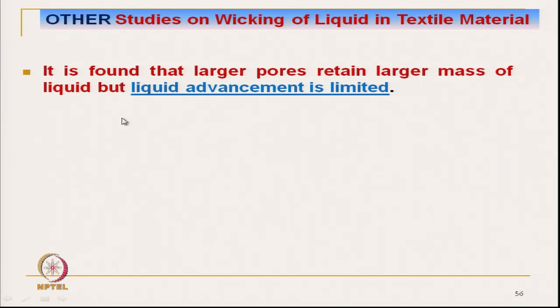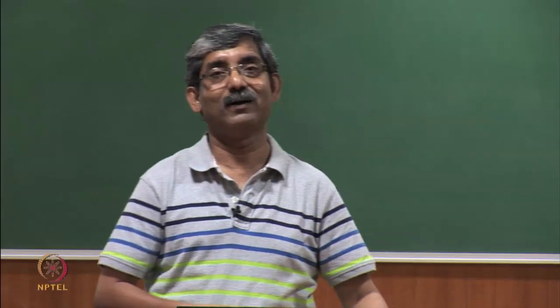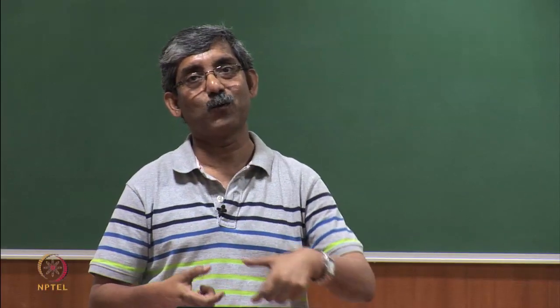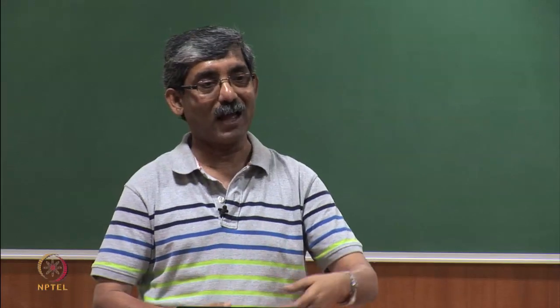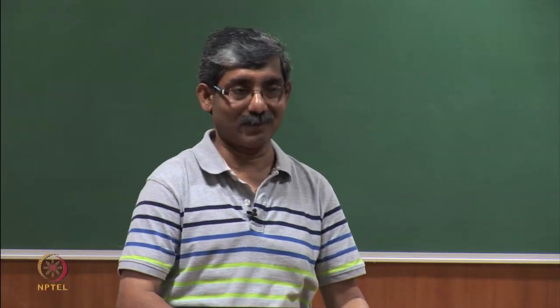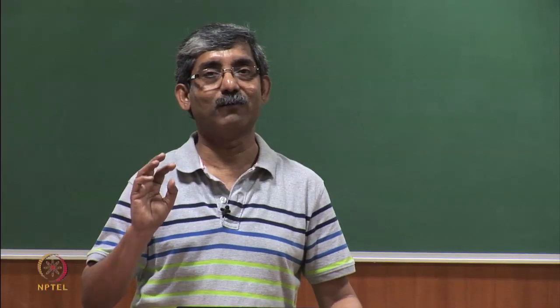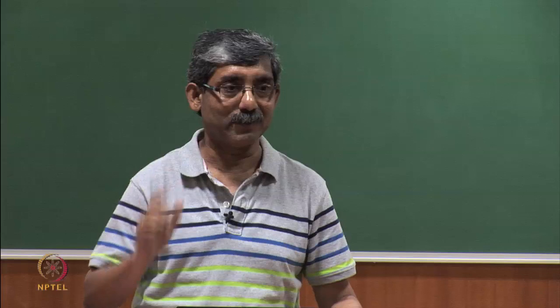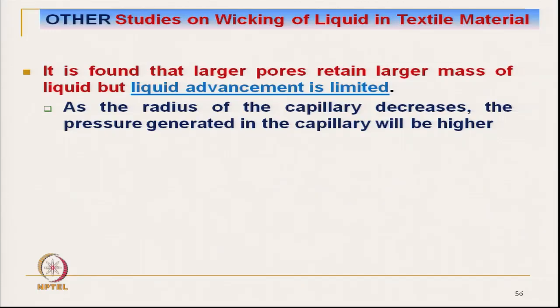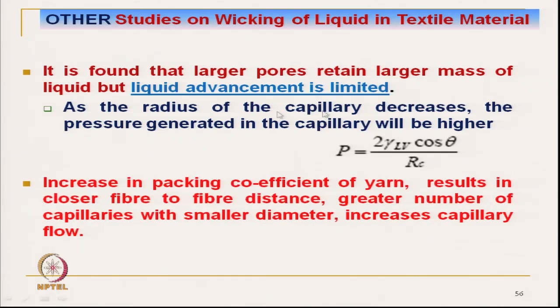But as we have just mentioned, if the pore size is larger, it will actually limit the advancement of the liquid flow, due to the higher pore diameter. As the radius of the capillary decreases, the pressure generated in the capillary will be higher. So, that means we have to have higher porosity, but the pore diameter should be small.